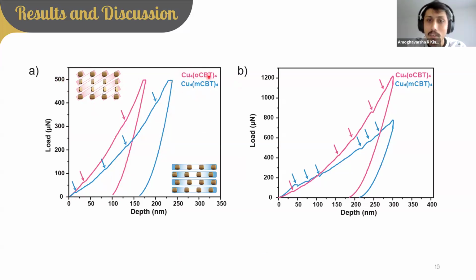indicating Cu4 OCBT is slightly stiffer or slightly stronger. Again, coming to displacement controlled indentation, we specified a displacement of 300 nanometers, and we see that to attain the same displacement, Cu4 OCBT requires a larger force compared to Cu4 MCBT. Again, indicating Cu4 OCBT is slightly stronger than Cu4 MCBT.